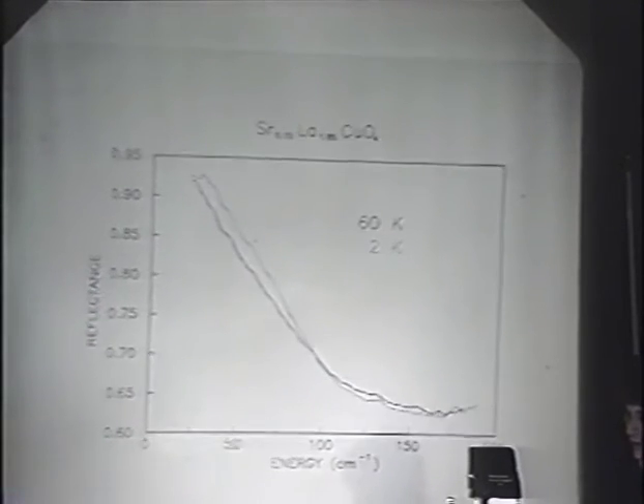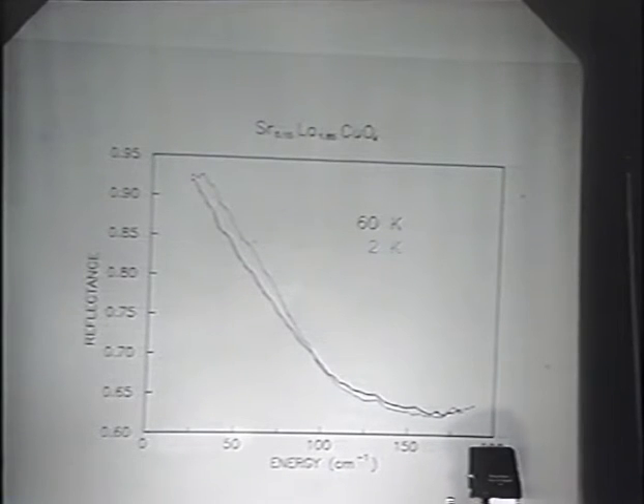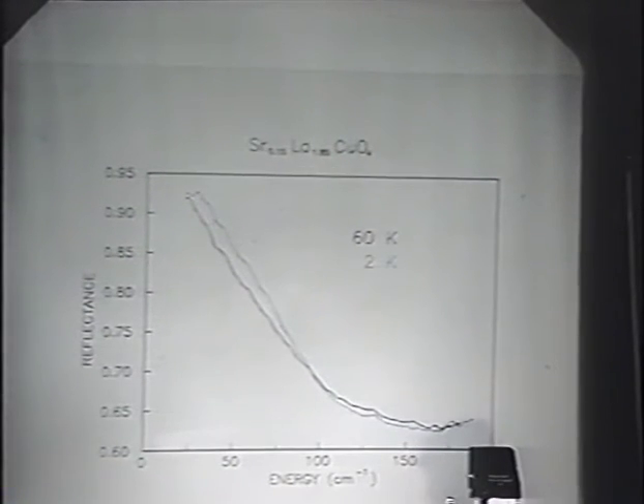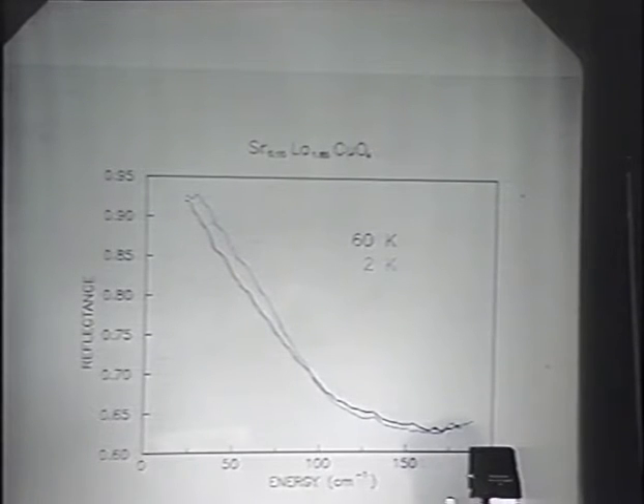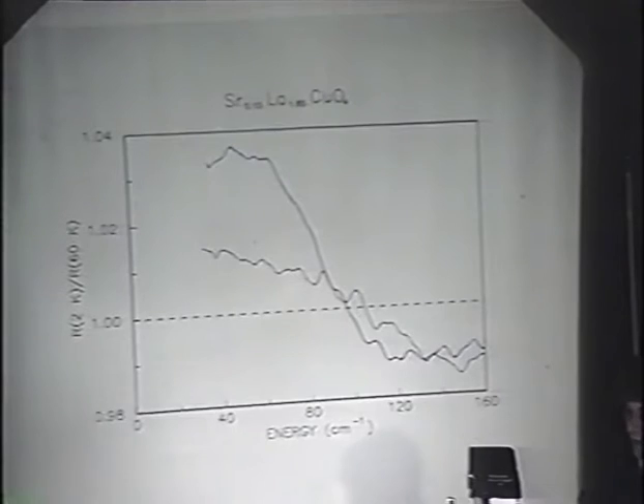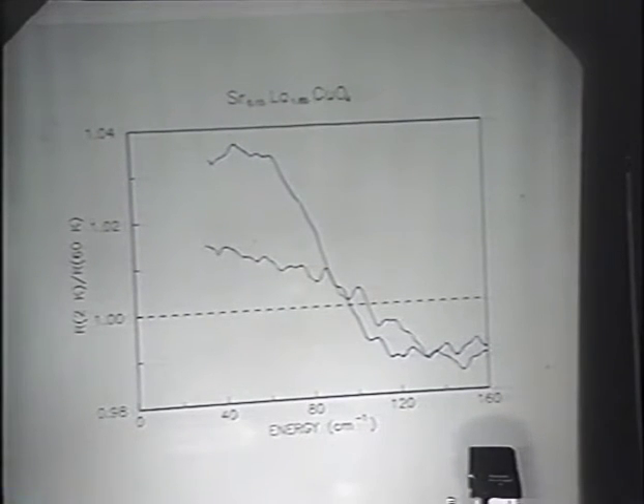The blue curve here is in the superconducting state, and the black curve is in the normal state. We don't see the full 100% reflectance that you'd expect in the superconducting state in this material. We take this as a sign that we're seeing a large fraction of normal state material still in the sample. However, when one takes the ratio, one can still get a reasonable idea of what the energy gap might be in this material.